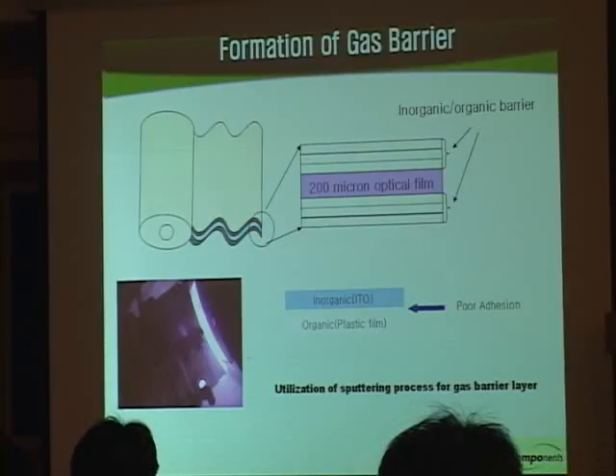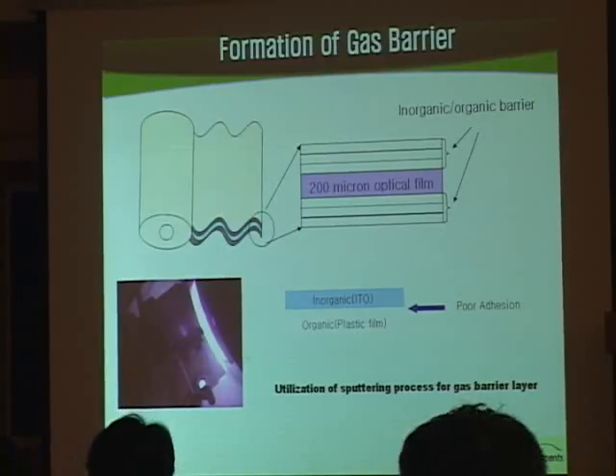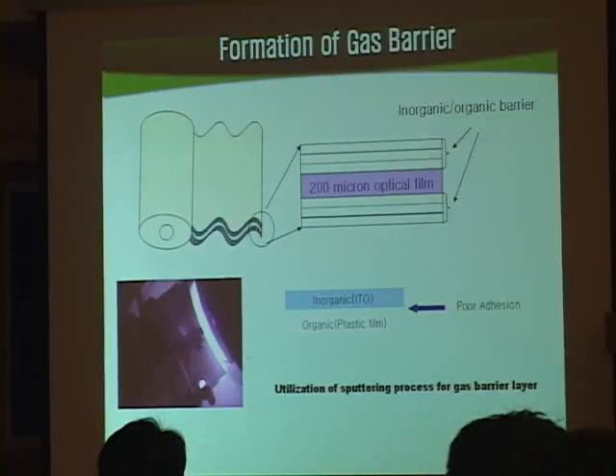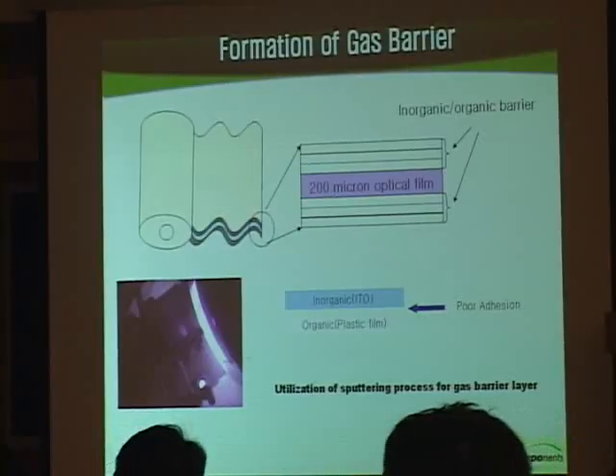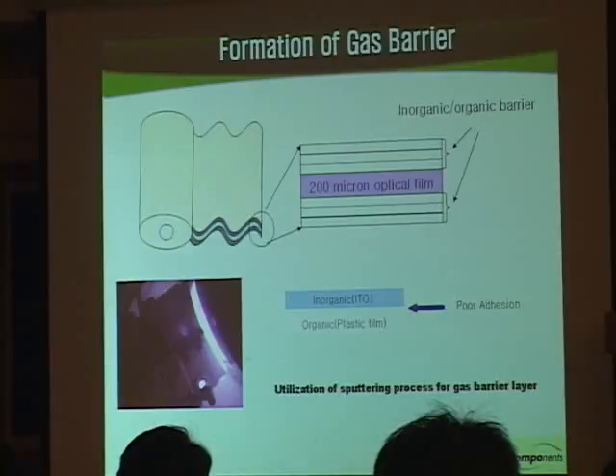However, the problem is the substrate will go through a different type of display manufacturing process, and it's not enough. So we need to put some other material on top, or beneath this sputter layer, gas barrier layer. So then comes the question of adhesion of organic material and inorganic material. ITO is one example, or some other gas barrier materials is another example. So we need to improve the adhesion property, and that certainly is very important because we could make a certain substrate and then send it out to the display manufacturer.